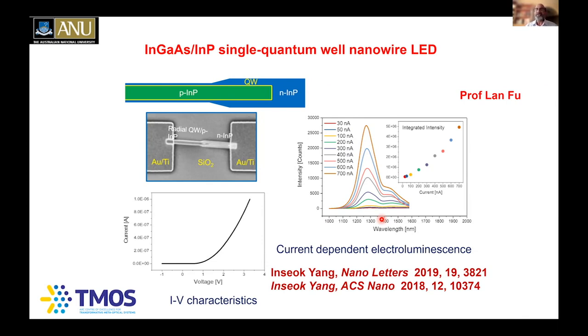Also, the smaller the laser, the less energy they consume. The smaller the laser, you can switch them on and off faster for faster communications as well. So that's why we're interested in this. But now you can see from this one, you do not see any narrowing of the line width, which I've shown you earlier in the case of lasers. You also don't see any threshold-like behavior, which I've shown you here. And this is mainly because they are acting like light-emitting diodes, not like lasers. This particular work is also led by my colleague, Professor Lan Fu.